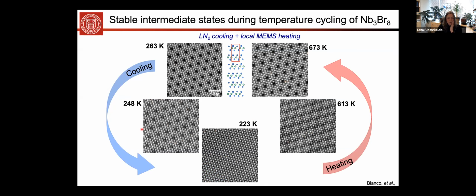So these are actually just 2 intermediate temperatures. We have many, many more to show. And first of all, this result shows that in these thin films, the hysteresis becomes very large. You see that we have to go all the way to 670 Kelvin to recover the high temperature state. But what you also see, or what I hope you believe me, is that there are many, many intermediate states that are stable. And that is quite interesting because it might suggest that there are intermediate magnetic states in these systems as well. And that might give rise to these broadened distributions in the hysteresis loops of bulk measurements.